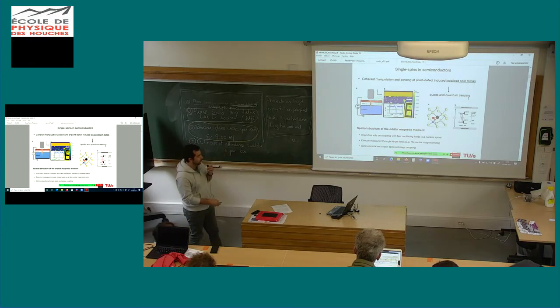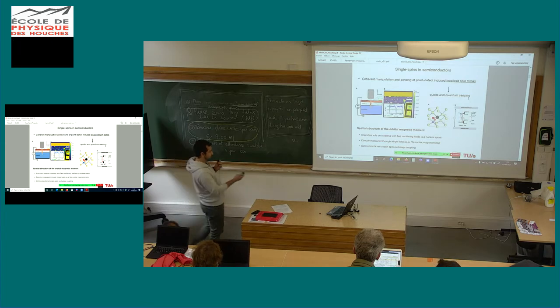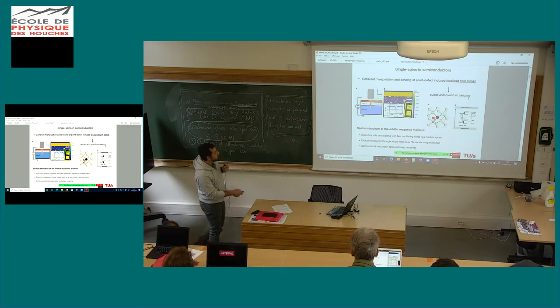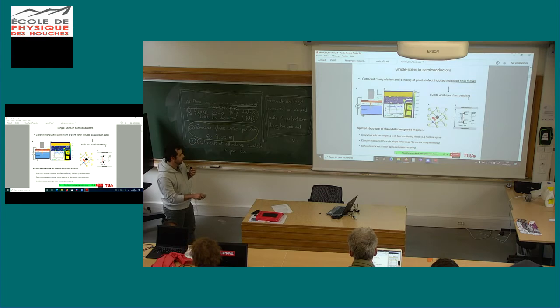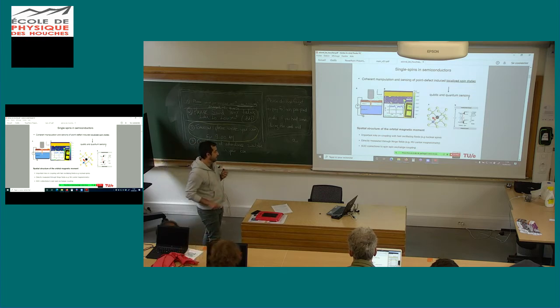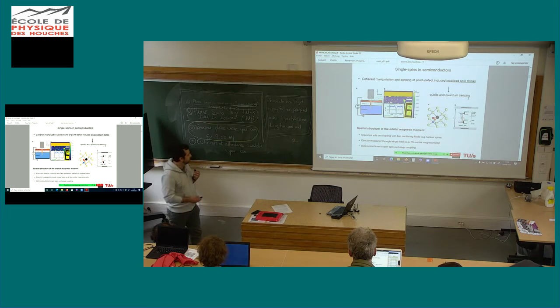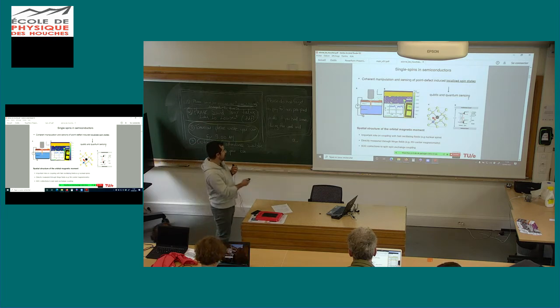I'm going to look just at the ground state properties. The spatial structure of those magnetic moments is quite important when we look at coupling with fast oscillating fields, like nuclear spins that surround the defect. I'll show later that these magnetic moments can also be directly measured by the fringe fields, and this can also be measured by these NV centers that I mentioned before. The most important ingredient in all of this manipulation is the spin-orbit coupling, and so I'm trying to develop a formalism that goes beyond the dipole interaction between spins.